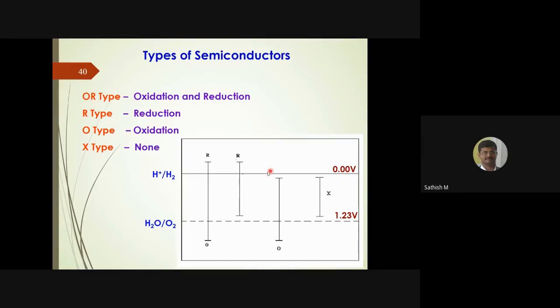In the case of the other system, that's the O type catalyst, you can do only the oxidation reaction. You cannot produce hydrogen. At any cost, you cannot use this particular catalyst for production of hydrogen. Whether it is oxygen evolution or any other reaction you use, you cannot make hydrogen evolution. If you select some catalyst which has the valence band and conduction band in between these energy levels, then you cannot do hydrogen evolution or oxygen evolution. This may be a good photocatalyst for decomposition of some particular dye or pollutant, no doubt, but you cannot use it for hydrogen evolution. So that is the point. Based on this water electrolysis, generally we can make different kinds of classification, majorly in 4 types.